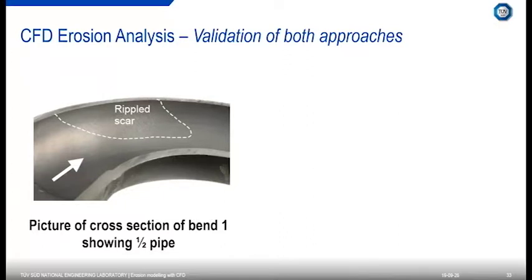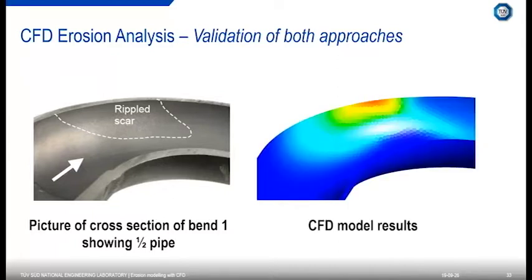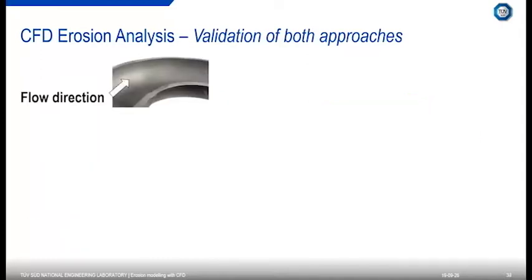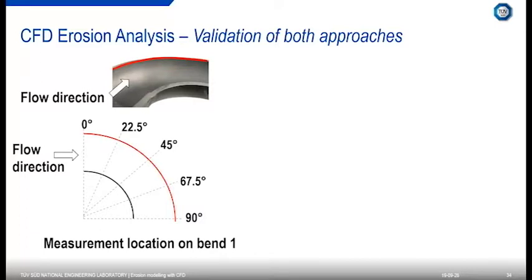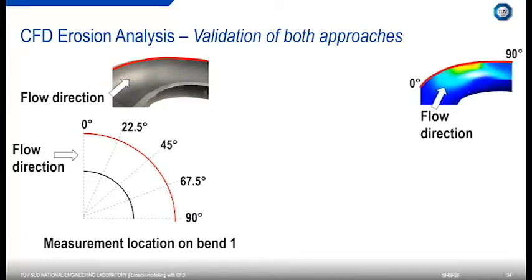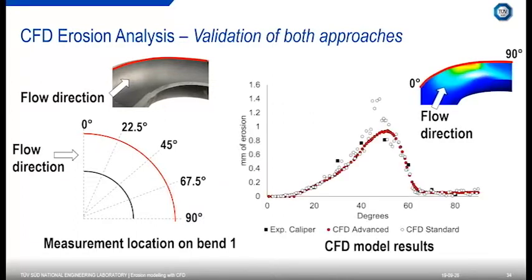We can see a picture showing the cross-section of bend one, showing half the pipe. We have this rippled scar that we can see. If we take the same image from the CFD, we can see that we're actually predicting the same trend. So that looks promising. We can take it a step further and take some measurements along that red line, along the outside of the pipe bend. This goes from 0 to 90 degrees, a 90 degree bend, and we can take various different measurements. And we can take the same information from the CFD and compare the two together.